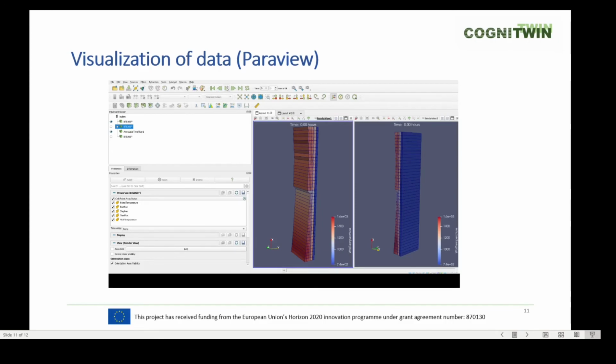So if we run this video, we see that when the metal is being filled into the ladle, it heats up very fast. In the lower part, it heats up by contact with the hot steel, and the upper part due to redistribution of energy by radiation.